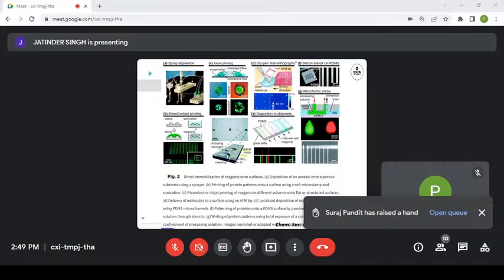You can stamp reagents in place, so you can make a PDMS positive structure and stick it into the material you want to stamp, and then put it carefully on the substrate. That means that you can get lines of one reagent or multiple reagents, and then allow the wet ink to dry, and that gets you a nice line of an immobilized reagent. Contact printing is kind of the same as the silicon stencil.